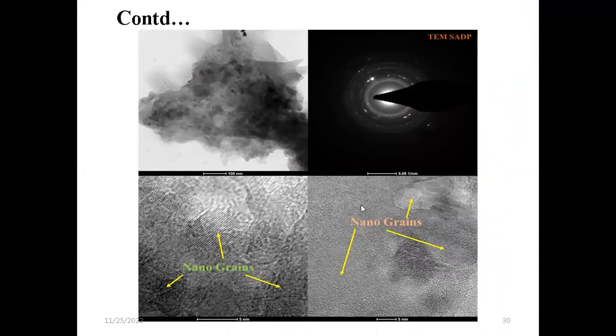And after that, the TEM analysis of the compact sample shows the diffraction rings with small star-like spots on each diffraction ring, which represents the phases that are present in the ball milled powder sample. And these are the nano grains that we can observe in the compact sample, where we retained the nanostructure upon sintering.